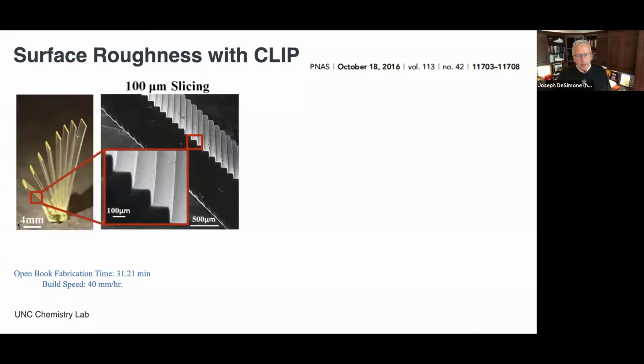But what's really interesting about this process is it's different in the sense that you don't have to run it always in a layer by layer approach. I love this little study here just to show you exactly what's happening. If you take this test pattern and you divide it into 100 micron slices and you print it continuously, what that means is that one given image will stay projected for 100 microns in Z. And then once you get to that threshold, you'll change the image again. And it'll go another 100 microns in Z and change it again, okay?